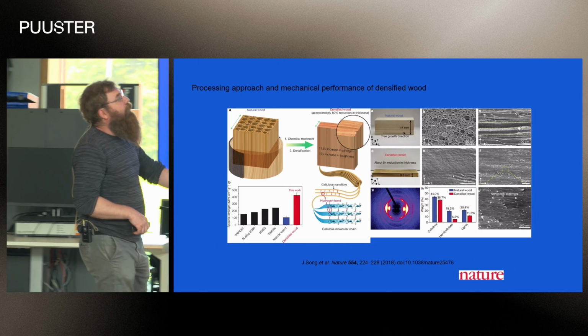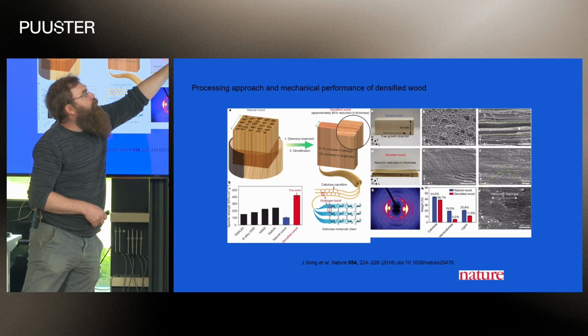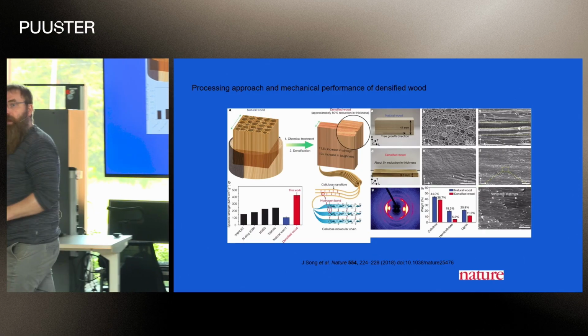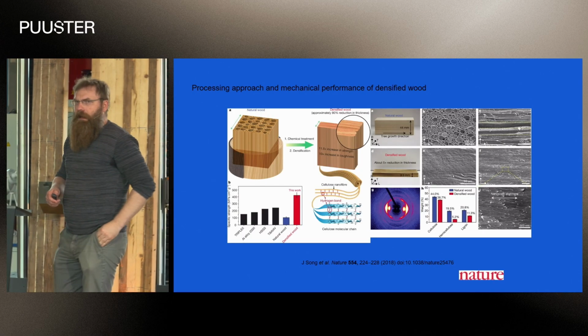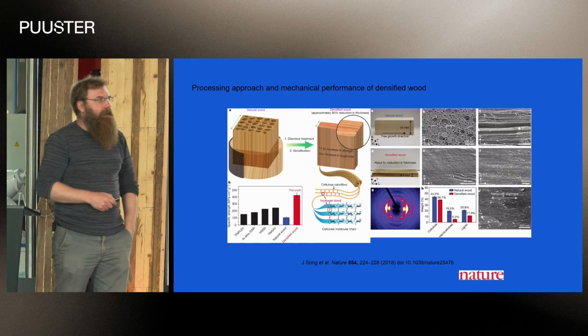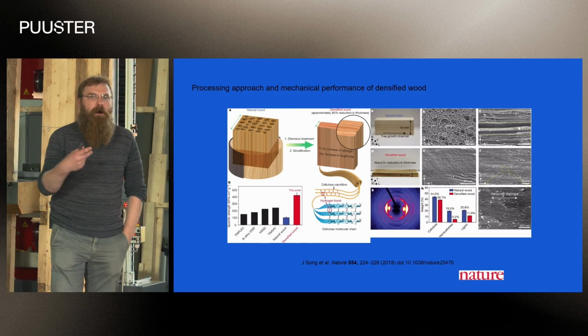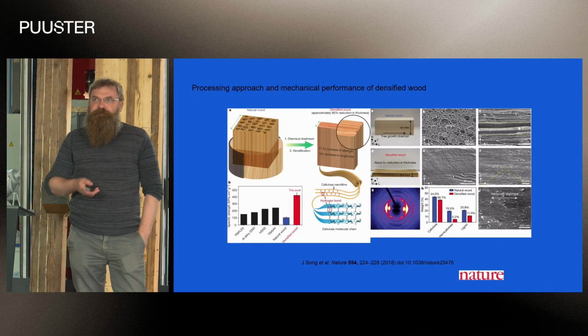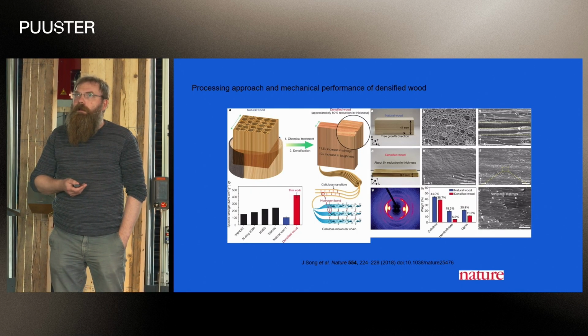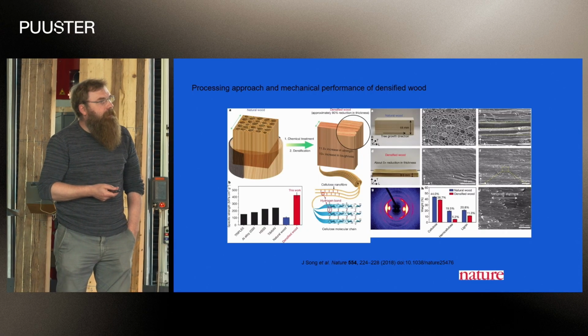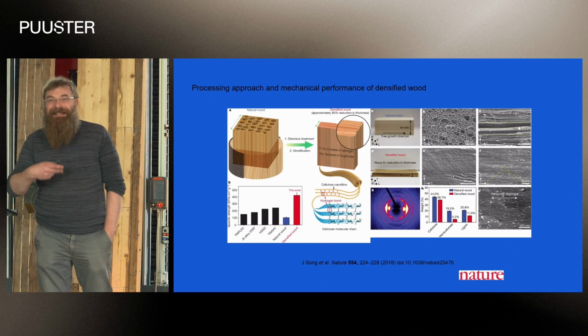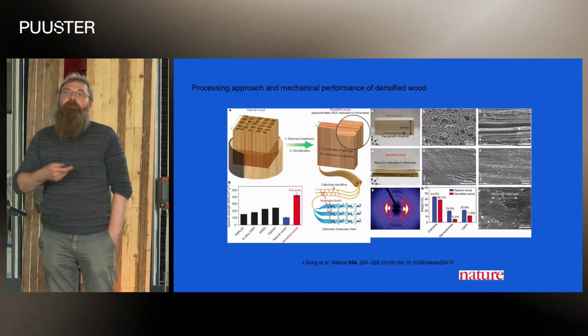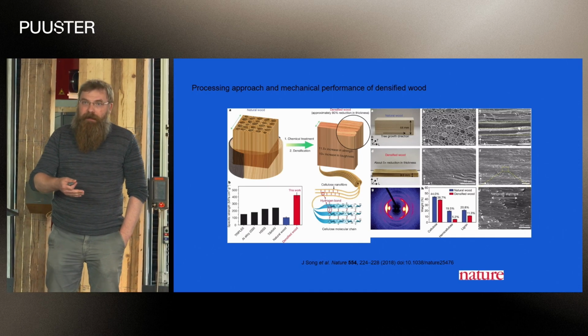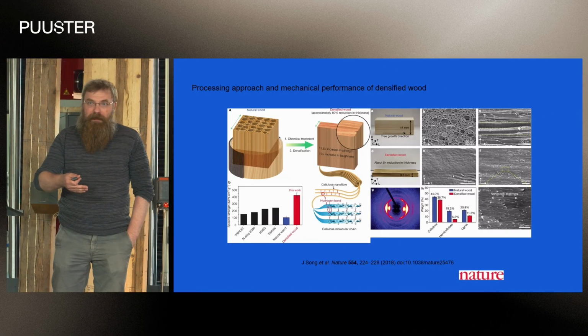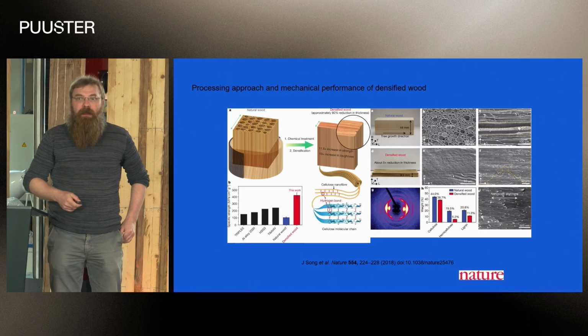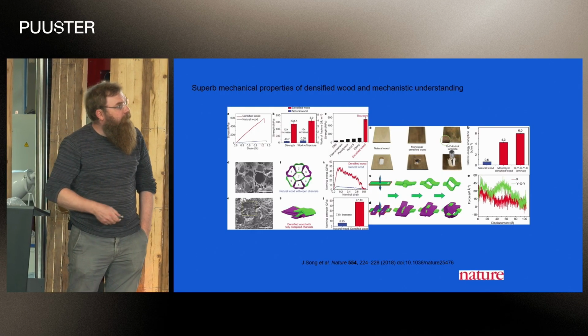And it turns out that you can quite cheaply make wood strong, a lot stronger than it used to be in the natural form, by removing some percentage of lignin, so the binding material, and by compressing it under heat and quite a high pressure. And the material that results has now a modified structure, so you don't have any more the open cells, but it looks like a solid material. And this material has now higher mechanical properties. So it's harder, it's tougher, and it's, let's say, stiffness. For example, when you normalize it with its density, their mechanical properties can be better than even titanium alloys. So the weight to strength ratios. And this is engineering wood.